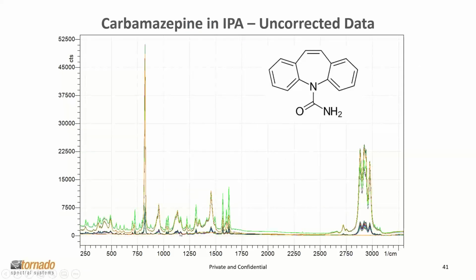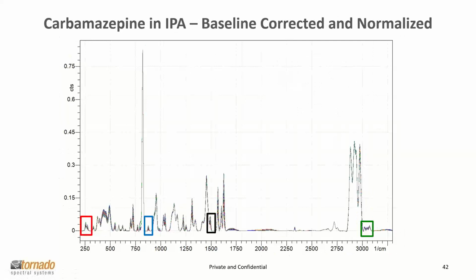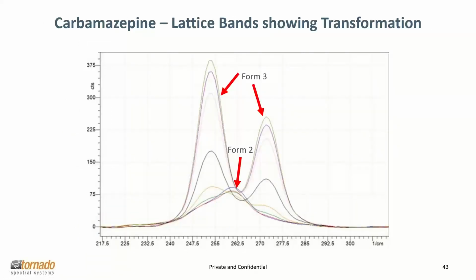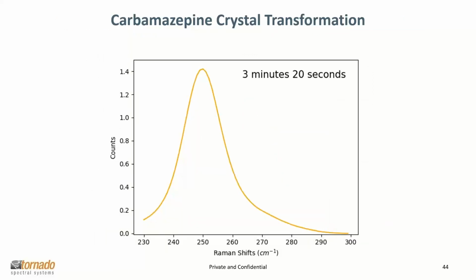Here's the spectral data, and you can see there's differing levels of intensity based on how much solid material is present. But if we do some corrections, do some normalization to the IPA band, and do some baseline correction, we can see some areas that are very interesting. One area Thomas already pointed out, which is down here in the lower level in the lattice bands, but there are 3 other areas that I'll highlight as well. We can see in that lattice band area form 2 converting to form 3, a very distinct peak pattern change that occurs.